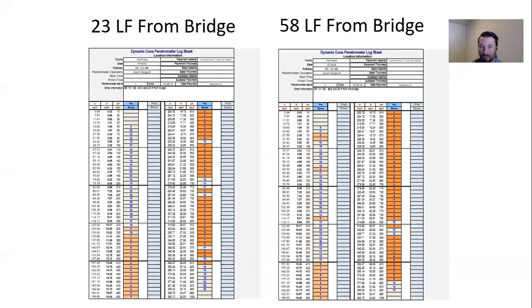In this project, again, under the direction of Keith, we did DCPs throughout the area, towards the center of the drive lanes. And as you're closer to the bridge, so here we've got 23 linear feet from the bridge, 58 linear feet from the bridge. Those deeper soils, we're seeing single-digit blow counts. That's what you see highlighted in orange. And ideally, using this 66-pound hammer, we're looking for 10 blows for 10 centimeters of travel. The DCP rods are marked every 10 centimeters. There's an engraved ring on the rod, and we're, again, just measuring blows of that hammer.